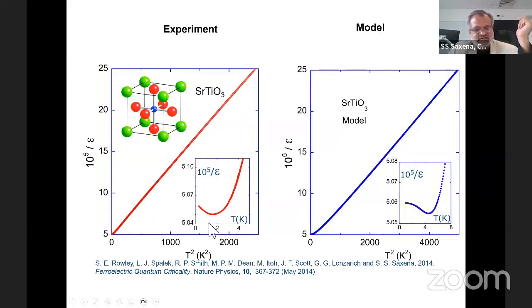So then you can see down. What is interesting is that at very low temperatures, we found that if you have a very precise measurement, just look at these numbers, 5.07, 5.04, that level of sensitivity, if you can achieve that, so experimental development is critical to finding this very subtle low temperature form of phenomena. You find some effect, and I'll go into this effect in a minute.